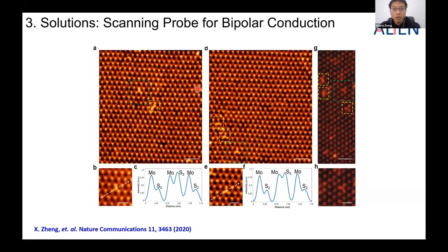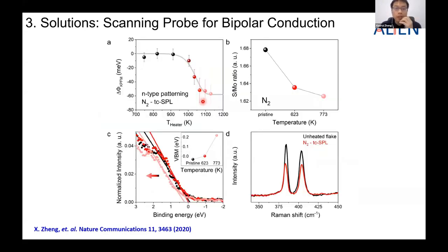Okay, so far we're using scanning probe lithography to demonstrate the p-type doping, and then we can simply change the environment chamber to different gases. For example, here we're using nitrogen gas. Instead of converting the material to p-type doping, we introduce n-type doping. This is the n-type doping level as a function of the temperature of the heater. As you can see, we can achieve continuous n-type doping while we're doing the tip scanning